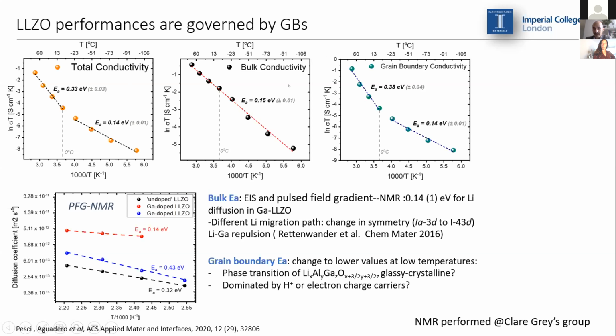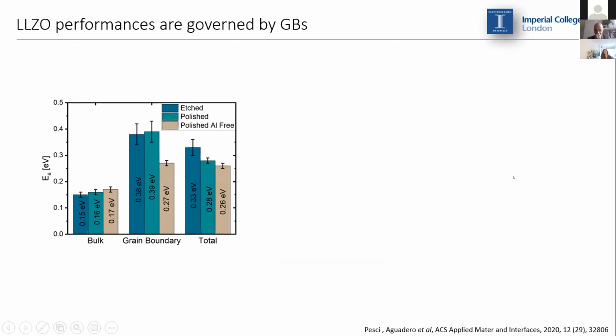The reason why we do have this change in activation energy is still not very clear. We are carrying out further experiments, but we do have two hypotheses. One, it could be that we do have an eutectic at the grain boundaries of lithium, aluminum, gallium, oxygen, which can actually undergo a phase transition at temperature below 0, for instance, going from a glassy phase to a crystalline phase. Or it could be that the grain boundary is dominated by proton or electron charge carriers. There is an ongoing study.